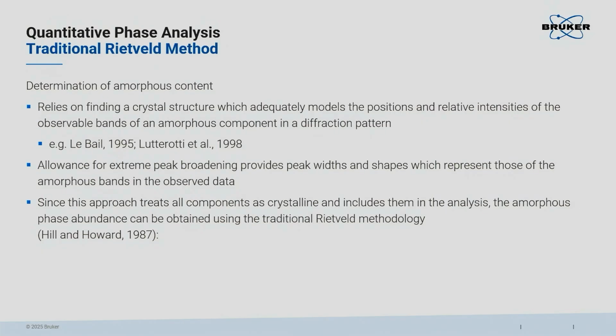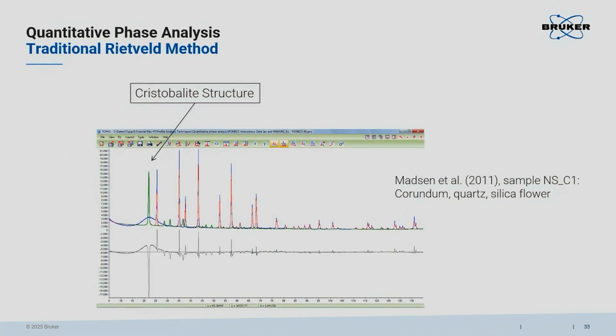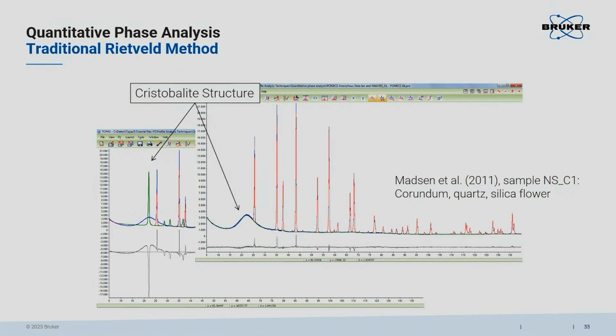As for the determination of amorphous content, there is a tiny chance to model amorphous content in the Rietveld method if you know the crystal structure of your amorphous material and if you broaden your peaks extremely. This workaround would then allow you, for example, in this data set, to use a cristobalite structure to model silica flour. And by extreme broadening of your peaks in your pattern, you can approximate the intensity distribution of your amorphous content. But you will find it very hard in practice for the materials you are working on to find a crystal structure which is sufficiently suited to describe your amorphous content and to use it in the refinement just by broadening the peaks. So I would say this is an exception and never the rule.